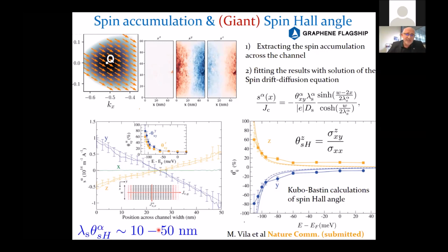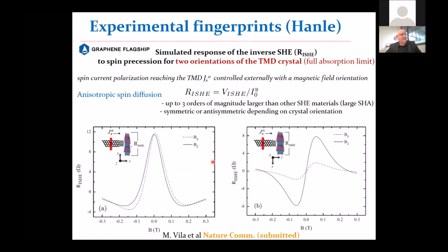Okay, in this work, actually, we also propose, because there has not been a non-ambiguous experimental evidence of the monolayer case. So in our analysis, our experimental colleagues have reported the signature of such a kind of anomalous spin Hall effect in this TMD material by doing Hanle spin precession measurements.